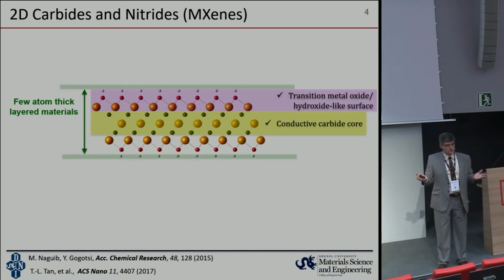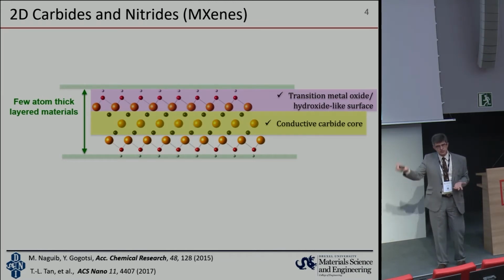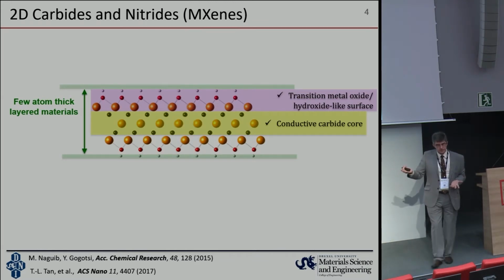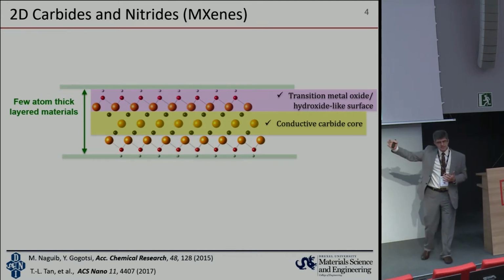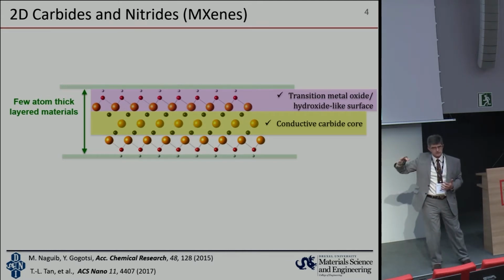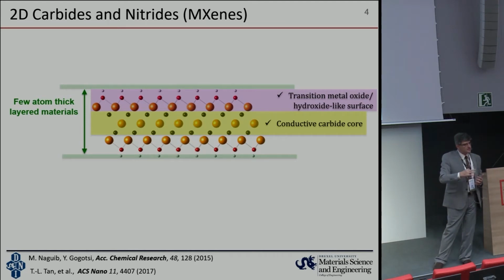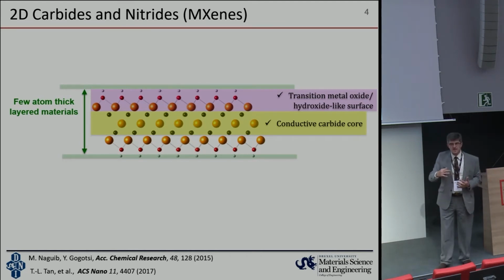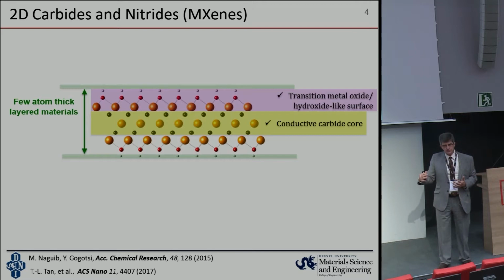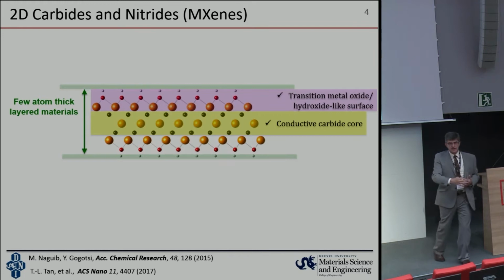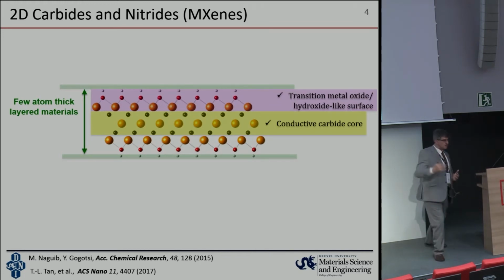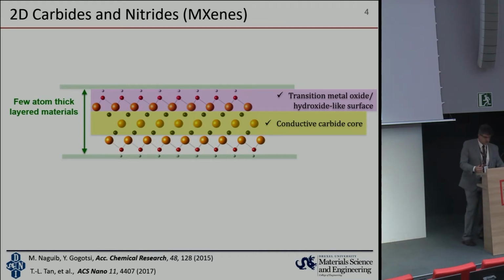So you can imagine materials that combine properties of a metal, being metallic, with a redox active surface with atoms that can change their oxidation state and do it reversibly. Moreover, you can attach something to the surface, polymer chains, functional groups, with relatively little effect on the electrical conductivity of the materials. If you modify graphene, for example, making graphene oxide, conductivity drops by at least 7 orders of magnitude. Here, you can attach functional groups and keep it conductive.